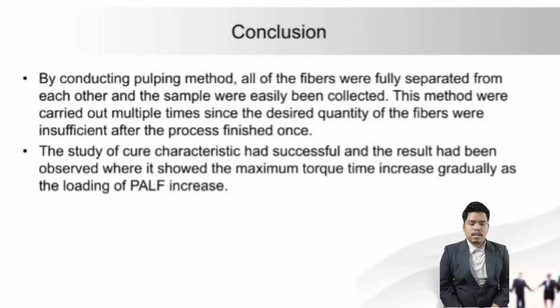For the conclusion, by conducting the pulping method, all of the fibers were fully separated from each other and the samples were easily collected. This method was carried out multiple times since the desired quantity of the fiber was insufficient after the first process finished. The study of cure characteristic was successful and the result has been observed, where it showed the maximum torque increased gradually as the loading of PALF increased.